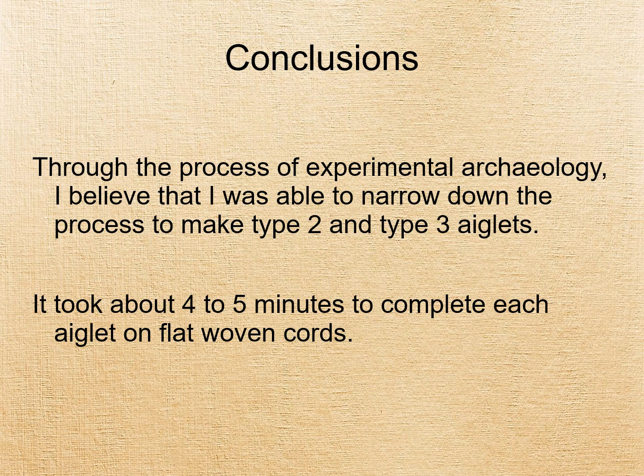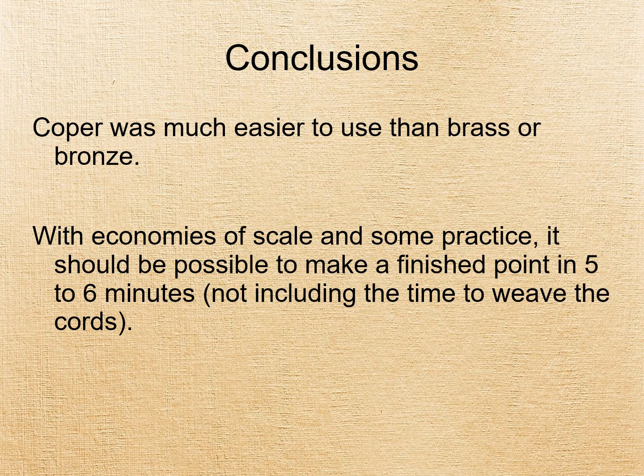It was also easier to use the thinner copper of about 0.12 millimeters to form the aiglets. Being thinner, it had fewer problems with work hardening. Thin sheets of commercial brass work hardened too quickly and required a lot of additional effort to make the edges smooth when making type 3 aiglets. It was also harder to get a uniform roundish shape to the type 2 aiglets with thin commercial brass.